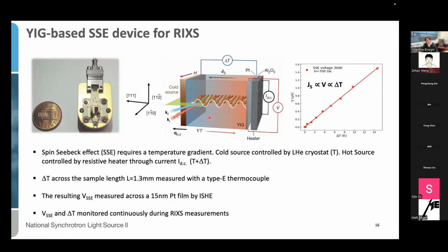So first of all, to have a Spin Seebeck device, we need to realize a thermal gradient across our sample. So this rectangular shaped piece of crystal here is our Yttrium Iron Garnet, and it is sandwiched between a cold source, that is what we call our cryostat extension on the side, with a copper piece, and a hot source, which is realized by a microelectronic heater.